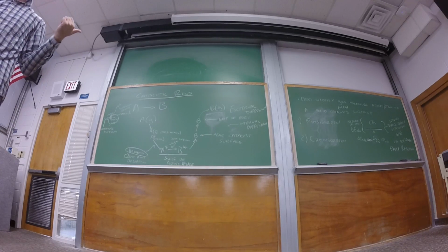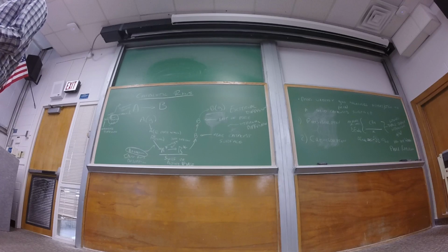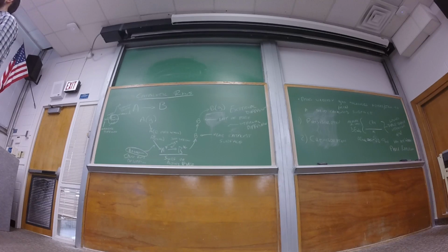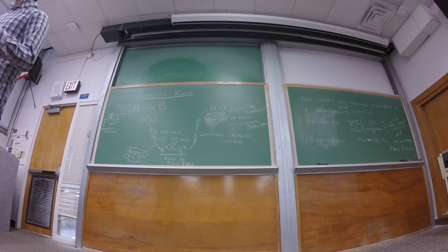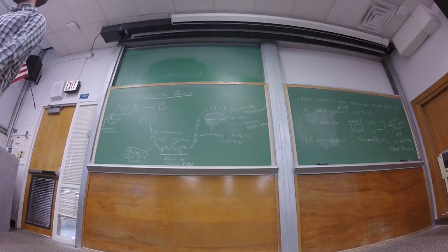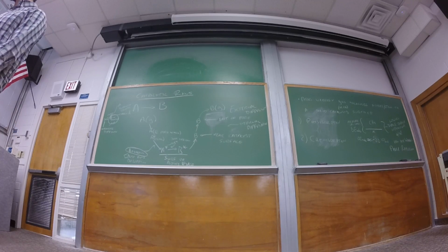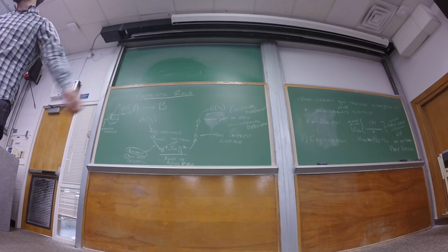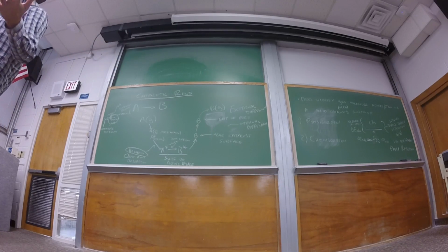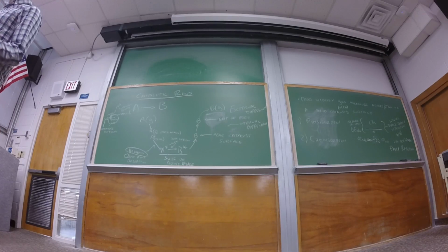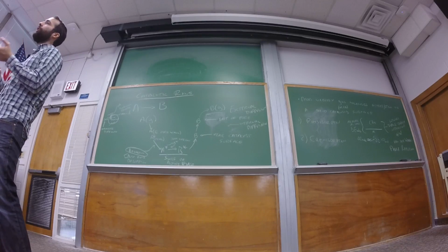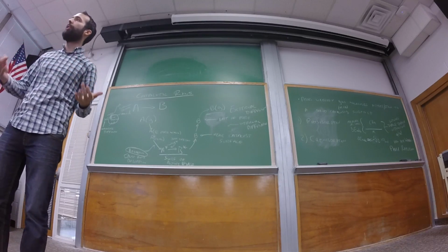The other way that you can do it with measurements is through calorimetry. So calorimetry is a way of getting a very precise measurement of how much temperature changes in a closed system. And so you create a closed system, you put in a very nice thermocouple, and you expose a metal to methane, and you see how much heat is released. Now, of course, you have to do it at conditions where the methane won't react, because then you're measuring the heat released from adsorption, but also the heat released from the reaction.